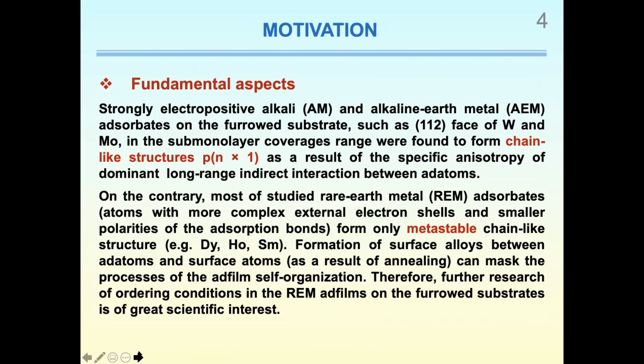And let's come back to the motivation of our research. Investigation of the structure of adsorbed films on furrowed substrates, such as the (112) face of tungsten and molybdenum crystals, revealed a rather long-range indirect interaction between the electropositive atoms through the substrate electrons. The specific anisotropy of this interaction creates adatomic structures which consist of linear chains crossing neighboring substrate furrows, and these chains are arranged at nanoscale distances from each other along the furrows.